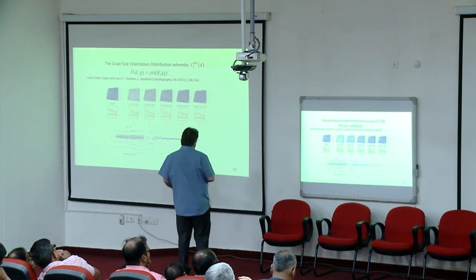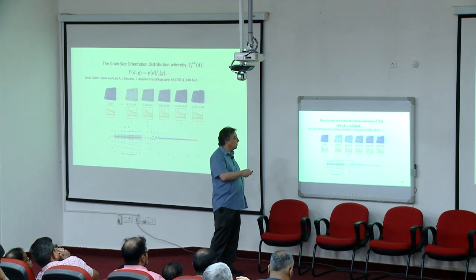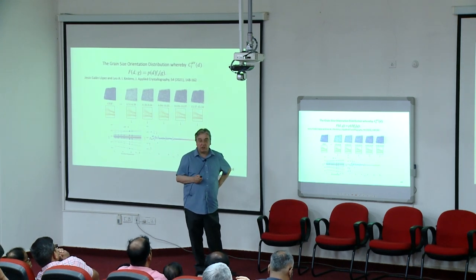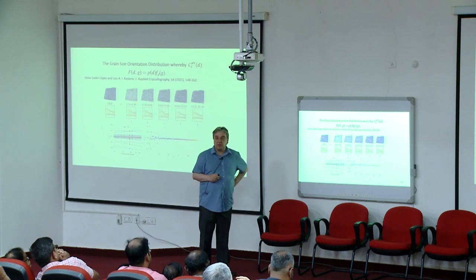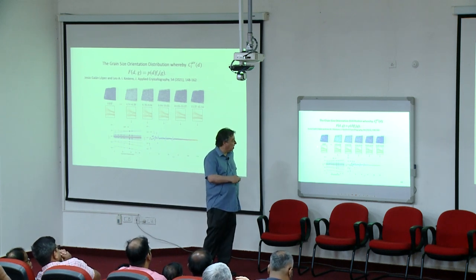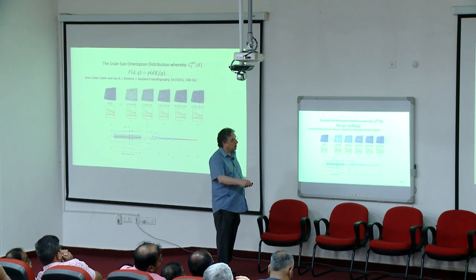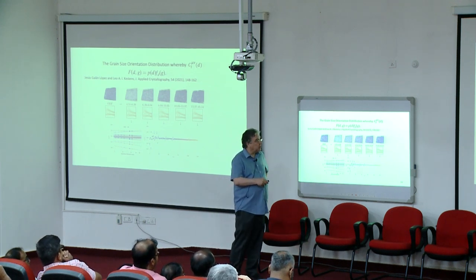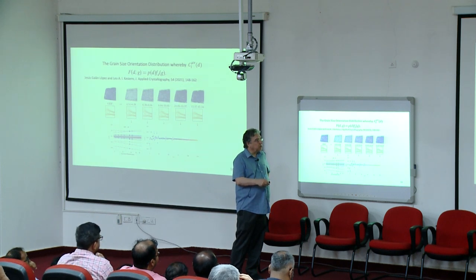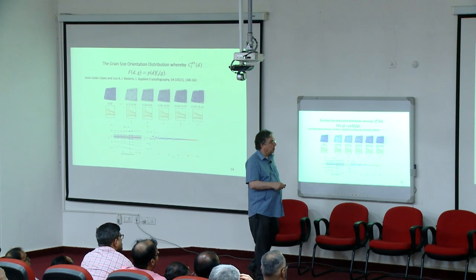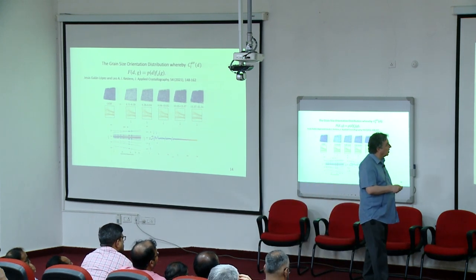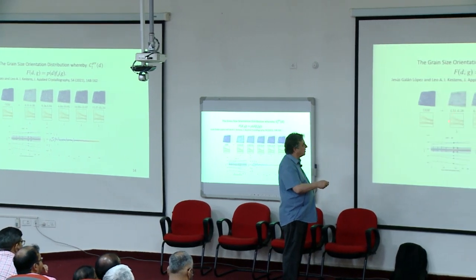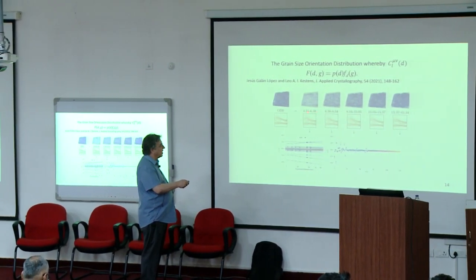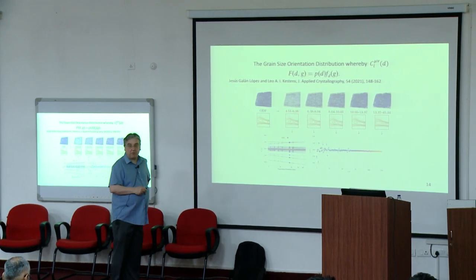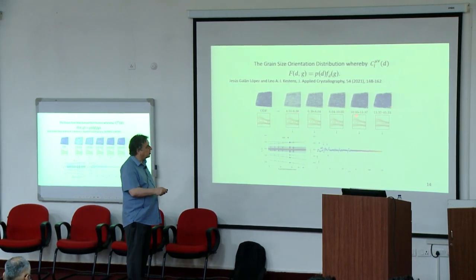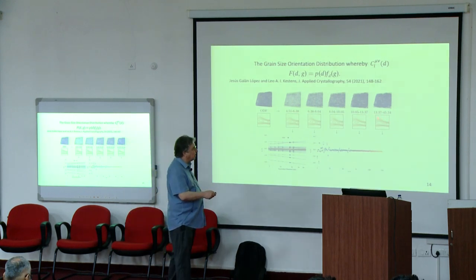Here we have, because we are much more familiar with working with the crystal orientation distribution function, the texture, we have a little bit extended this concept by also adding the grain size to it. So here you have all these different textures. They all belong to the same sample, but what is different is that they correspond to different grain size classes. So here you have the entire texture. These are the textures for the grains which have a size between 4.5 and 6.4 micrometers. And this is the texture for the grains that belong to the size category 13.4 to 45.3.